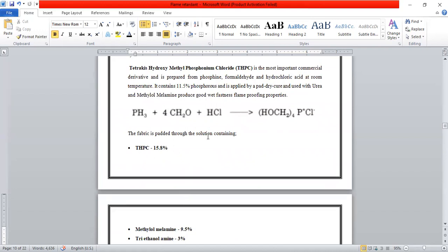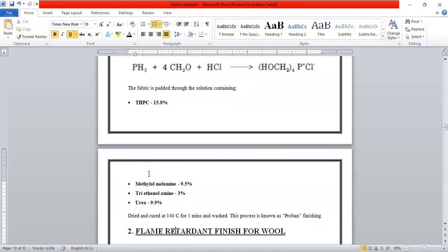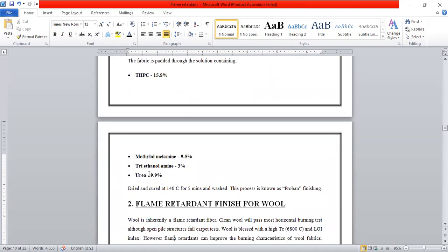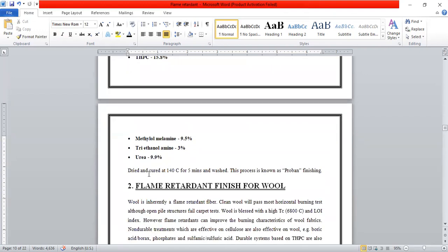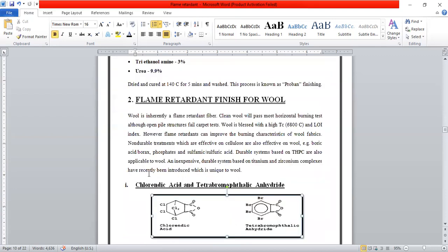The fabric is padded through a solution containing tetrakis hydroxymethyl phosphonium chloride 15.8%, methylol melamine 9.5%, triethanolamine 3%, and urea 9.9%. Dried and cured at 140 degrees Celsius for 5 minutes. The process is known as Proban finishing.